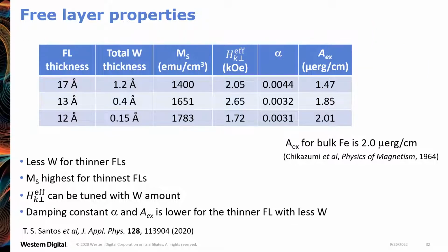Okay. If you actually look at this paper here, this is my paper, Journal of Applied Physics. I go into detail, and I actually do use layers of cobalt iron that don't have boron. But again, right at the interface, the free layer starts out with a cobalt iron boron layer because you need to have this solid phase epitaxy to happen. But then the upper layers away from the barrier have just cobalt iron, no boron. This is actually how you achieve the very high Ms values that I'm showing here, because there are some parts of it that intentionally don't have boron in it.